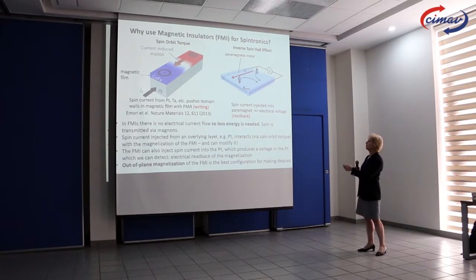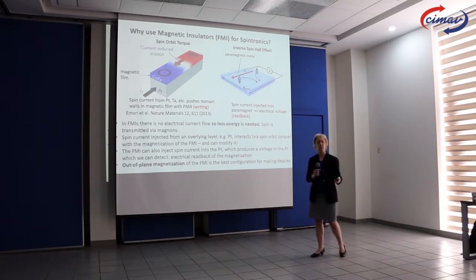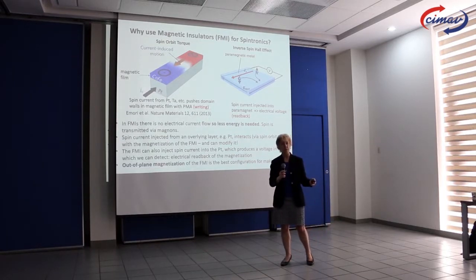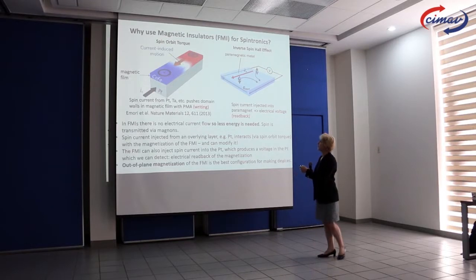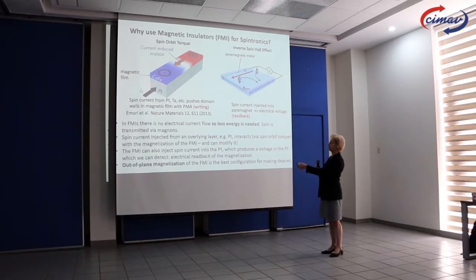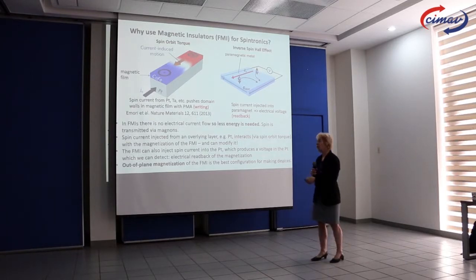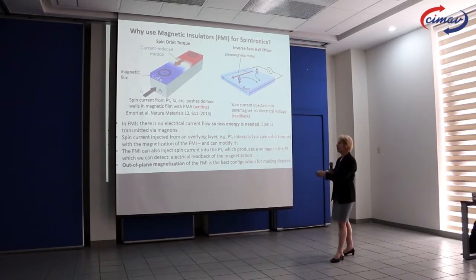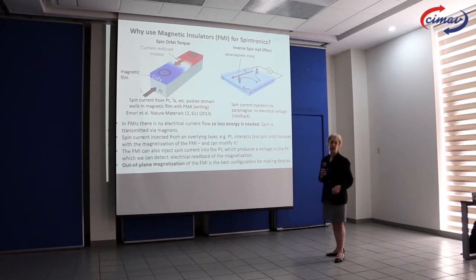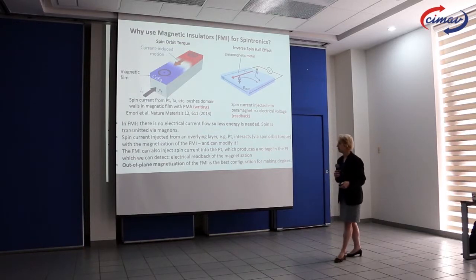Okay, so why do we care about using magnetic insulators like garnets? Why don't we just use magnetic metals like cobalt or iron? And the answer is that magnetic insulators don't have any electric current flowing in them. So if I make a structure like this, which has cobalt iron next to platinum, if I pass a current through the platinum, it will also pass through the cobalt iron. And so we'll have all kinds of different things going on, and we'll have a lot more energy being dissipated because it's flowing through two layers instead of one. If I replace this magnetic metal with a magnetic insulator, I know that all the current is going through the platinum, and I can minimize the amount of power dissipation.